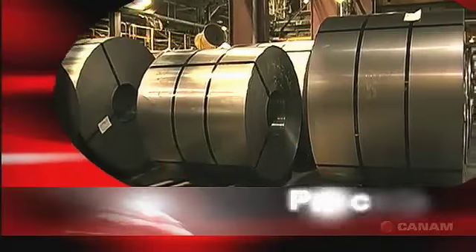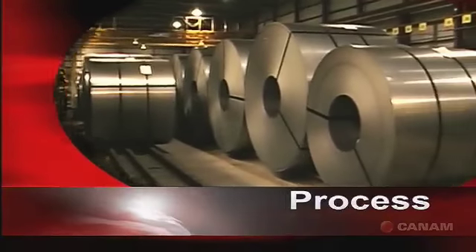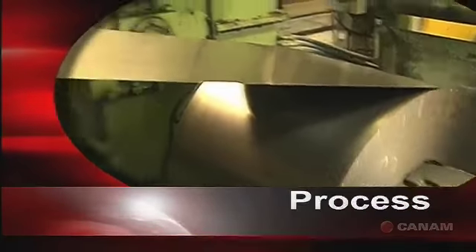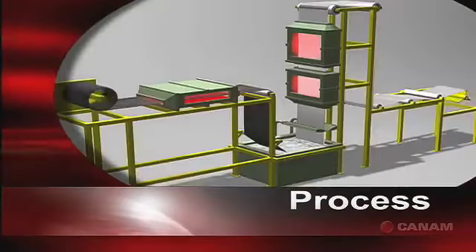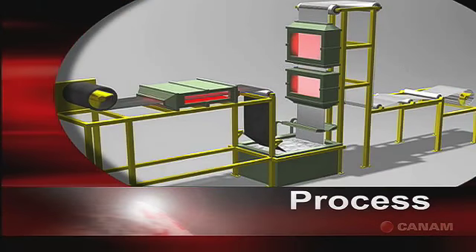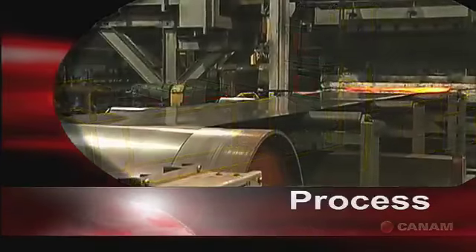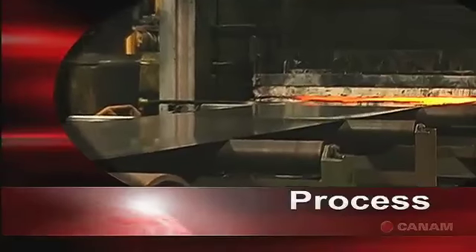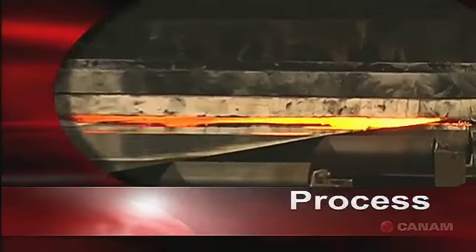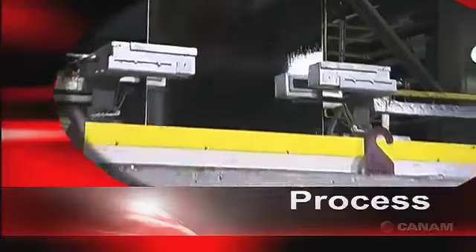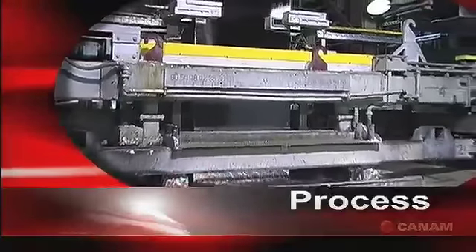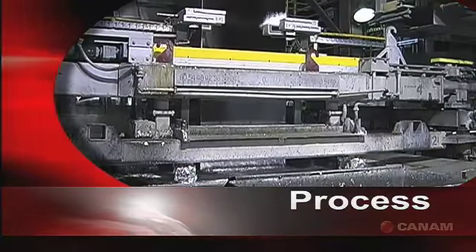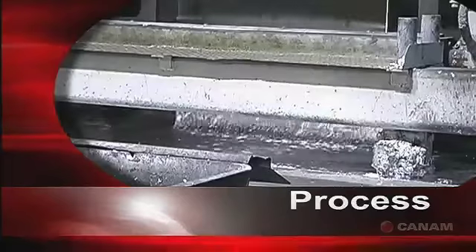The galvanization process is a continuous hot-dipped process. We receive the raw material in the form of steel coils, which we unroll to create a continuous strip for the galvanization process. We heat this steel at high temperature before dipping it into a liquid zinc bath. At the bath exit, we remove the zinc excess with air jets to control the quantity of zinc in the coating and create a uniform surface.